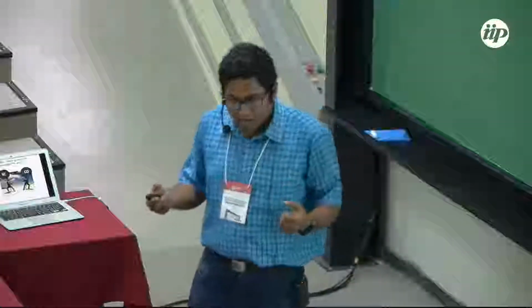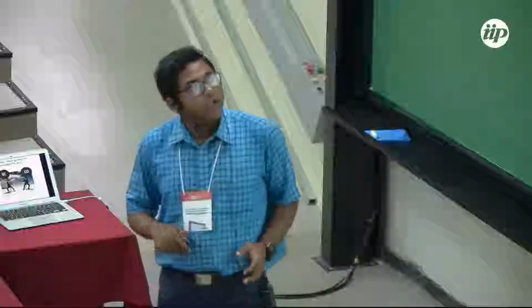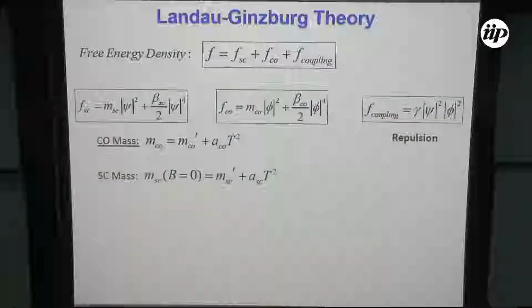So in order to understand the competition between two orders, we have started using the Landau-Ginzburg theory, where what we do is that we put a free energy like this, where we have a superconducting component, we have a charge order component, we have a coupling between the two. The superconducting and the charge order component both have a phi-4 form of the free energy. I will call the coefficient of the squared terms the mass of each field. So this would be the mass of superconductivity, this is the mass of the charge order. And we introduce a coupling between the two fields like this, and we take it to be positive because they don't like each other, they compete with each other.